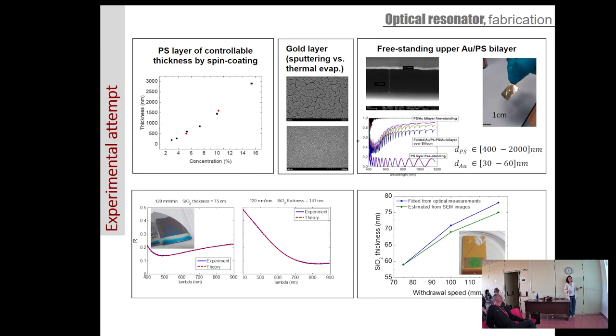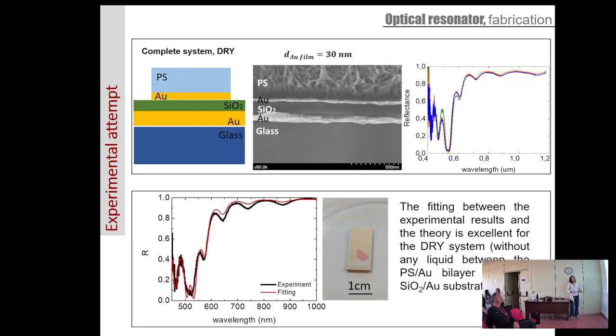Just here to show you that we were fabricating the polystyrene layer and then checking the optical quality of gold. We could fabricate our freestanding system with high optical quality. Then we fabricated two different substrates, not just the gold one but the silicon one also, a silicon wafer with silica, and here the same. So we can check the optical quality and the size of our sample. We really wanted to observe macroscopically a quantum effect. We built the whole system without glycerol.